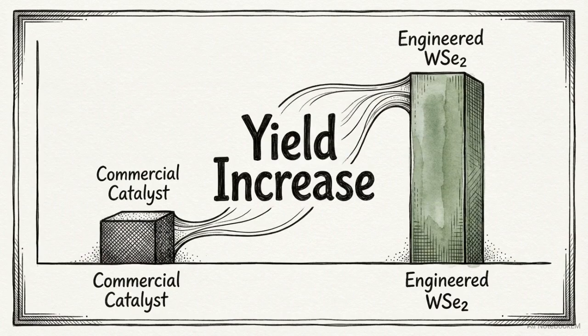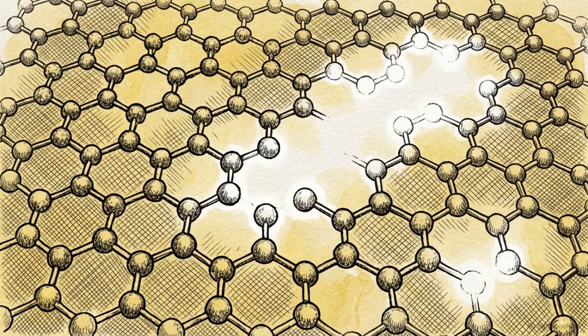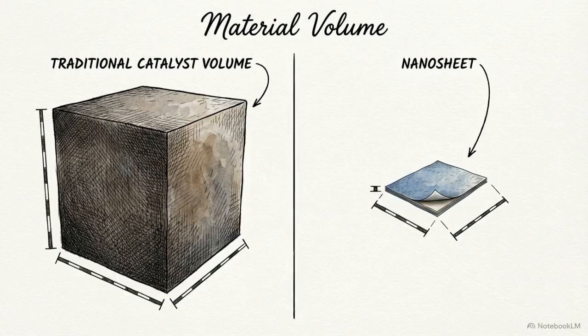Engineering these atomic defects allows our ultra-thin sheets to achieve a 38% higher hydrogen production rate compared to standard commercial benchmarks. By deliberately breaking the material's perfect structure, we achieve high hydrogen yields while using 65% less precious metal overall, making green hydrogen economically viable.